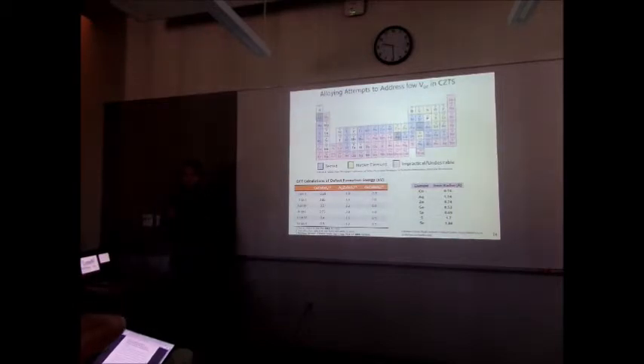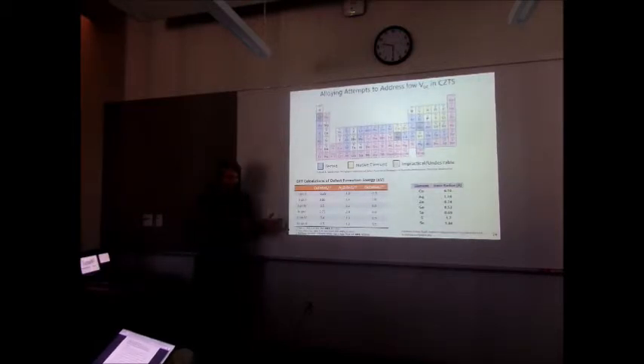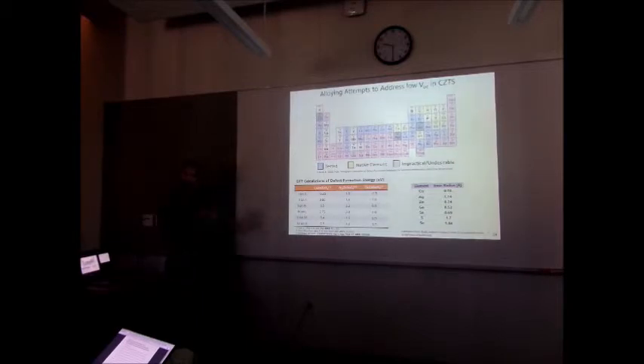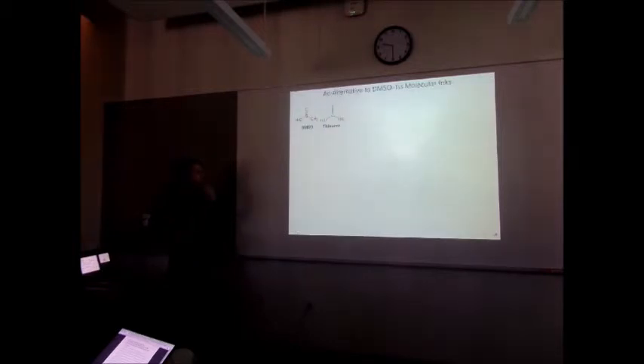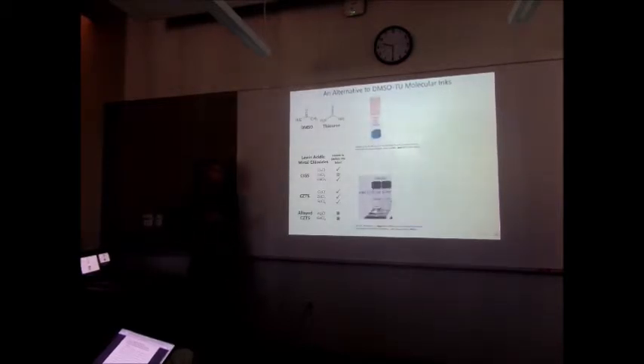So we really wanted to pursue this alloying strategy where we try and put in these materials, but we were having some problems. And this led us down a pathway of looking at different things, of ink chemistries, and it ended up being a paper in itself. So everything I've presented so far is the DMSO thiourea process, molecular ink, but this has some limitations. Here's some work by my colleague Andrew again, who looked at germanium chloride ink, and it completely turns into a gel whenever you add germanium chloride into DMSO.